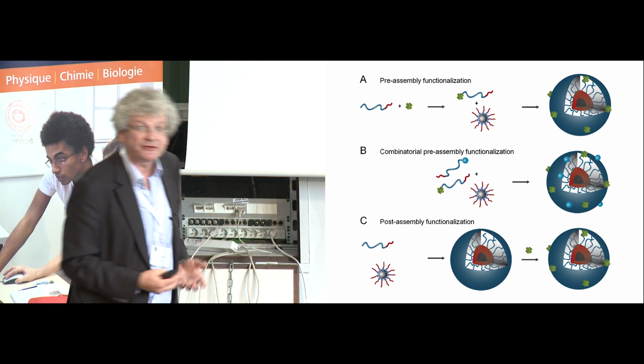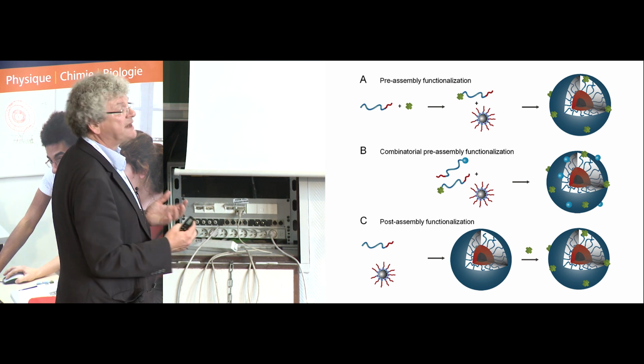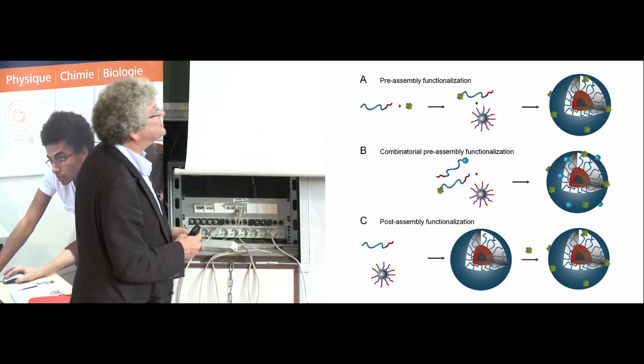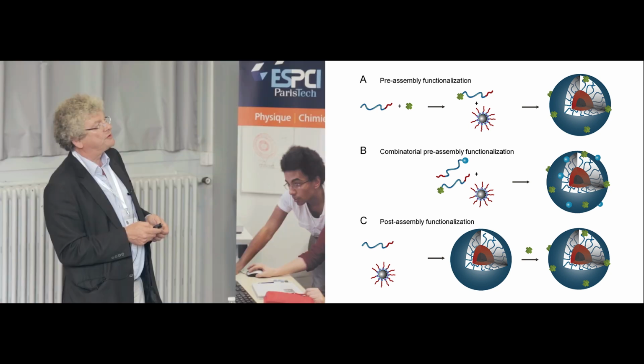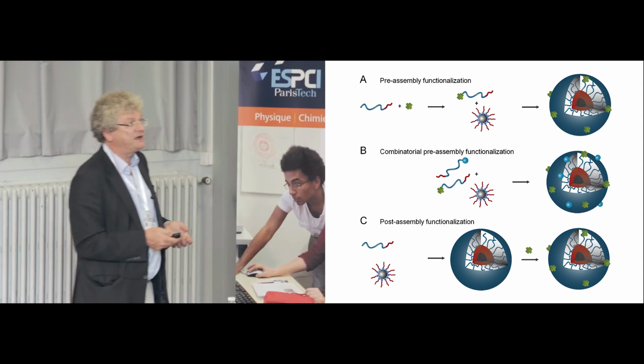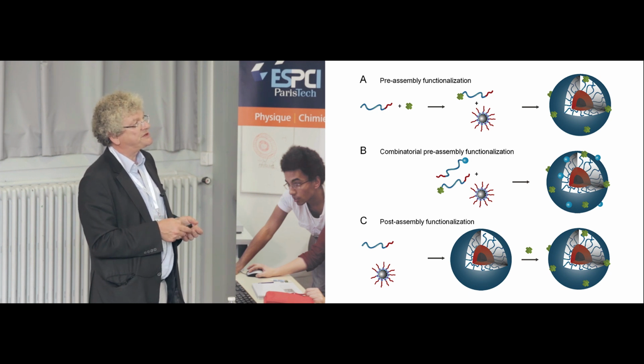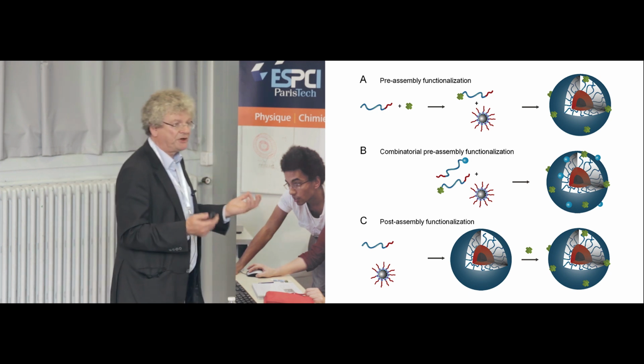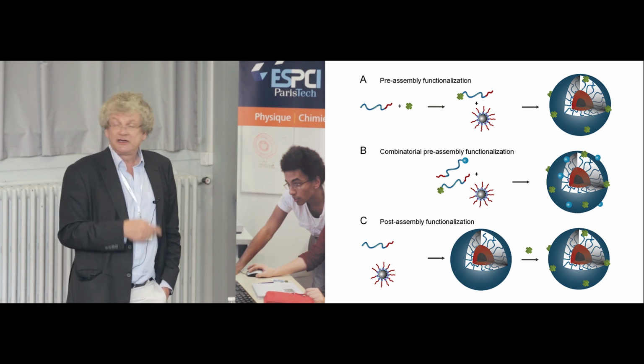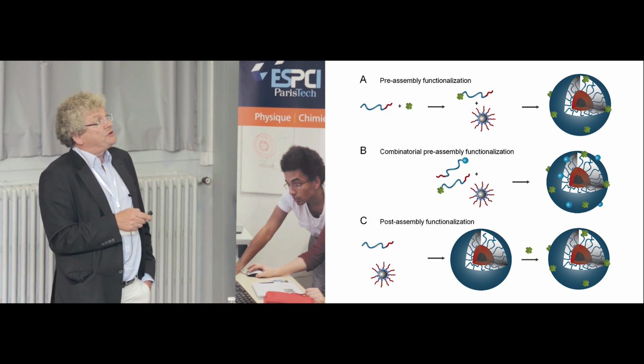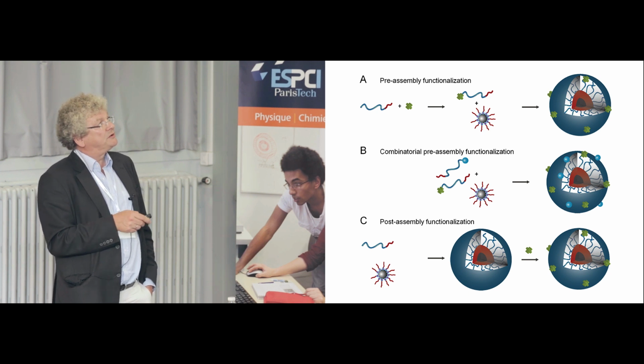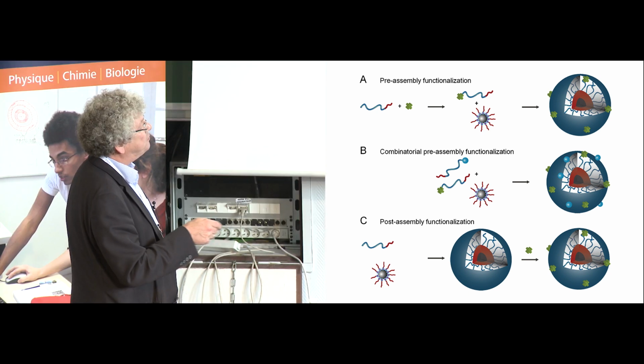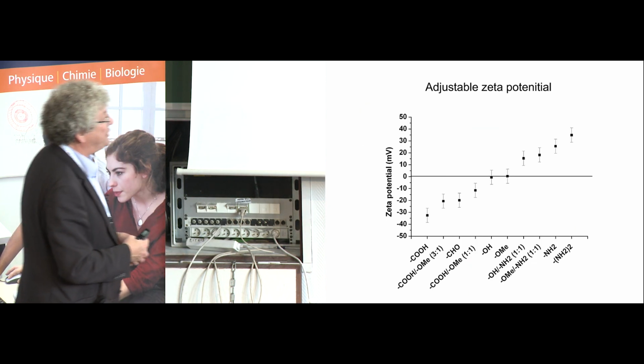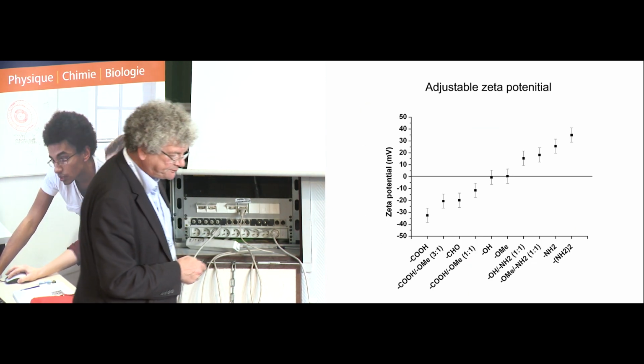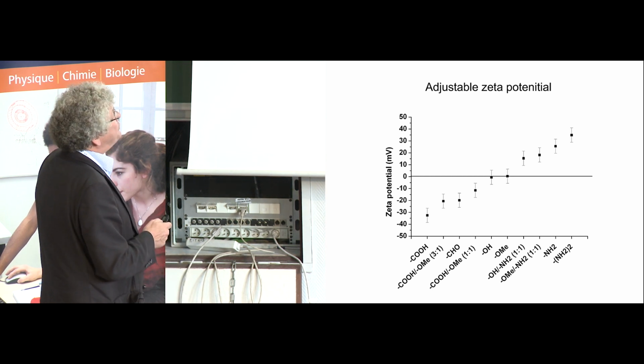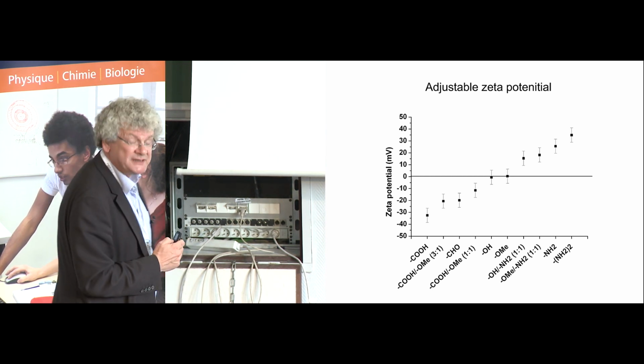And that allows, of course, combinatorial approaches and helps to understand how, for example, multivalent interactions and things like this occur. It doesn't work, of course, for very sensitive materials like antibodies. Then you have to do this post-assembly classical conjugation chemistry, which is also possible. Just an example to see how you can easily adjust by these combinatorial approaches the zeta potential by mixing charged and non-charged ligands. And here I show you a brief result on how to optimize these systems.